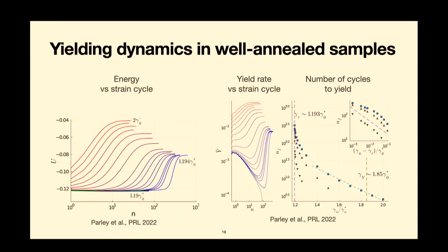So you have something where dynamically you have some kind of reentrance, where the system always almost reaches an elastic state, and then at the last minute it turns around and refluidizes. That's interesting because that's not necessarily what you'd expect. You might expect that the system either directly goes to a fluidized state or directly goes to a frozen state. Here what happens is it more or less misses the frozen state by a little bit, and then eventually still goes to a fluidized state.